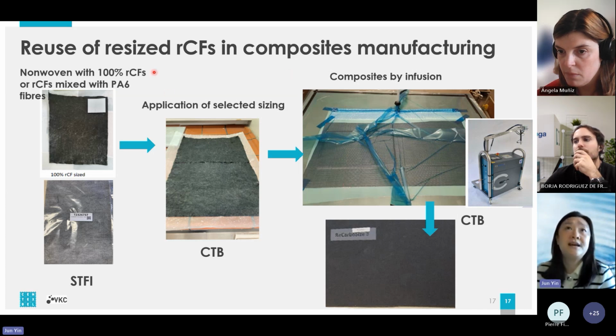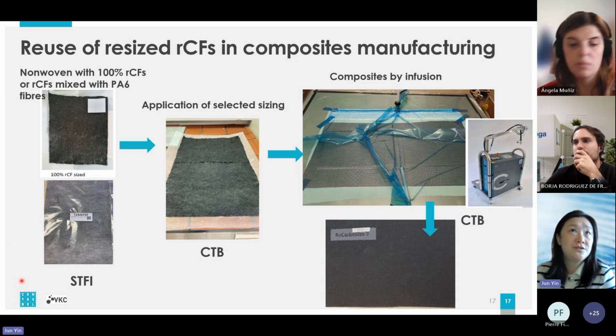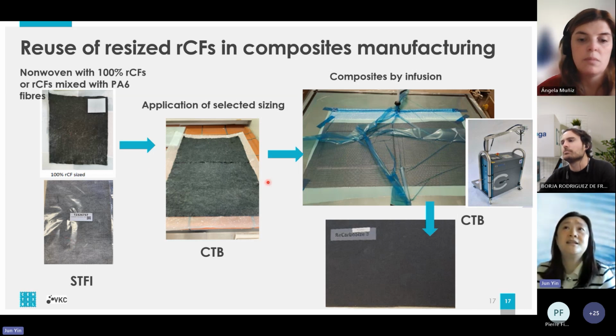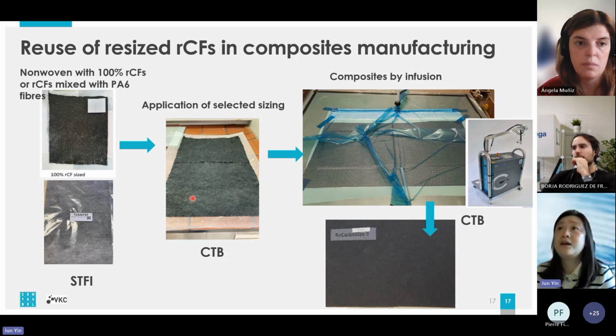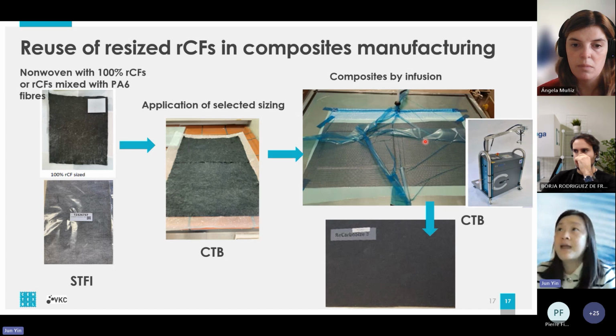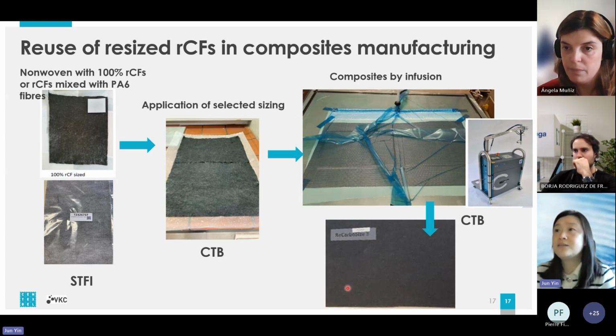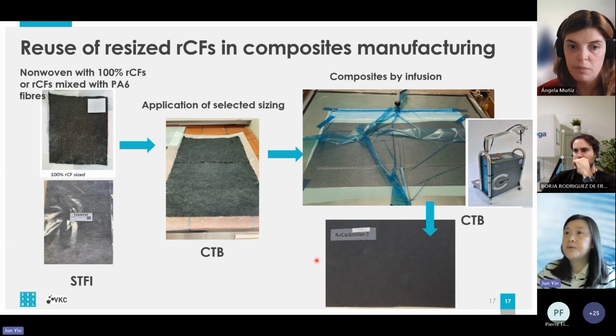To reuse this resized carbon fiber in composite manufacturing, STFI tried to fabricate different nonwoven structures. You can see here there's 100 percent recycled carbon fiber, and also the recycled fiber mixed with polyamide fiber with different percentages. Then we applied the selected sizing formulation to these nonwoven structures. Then we consolidate all these fibers into composite by the vacuum infusion method with epoxy. Then we get all these composite samples.